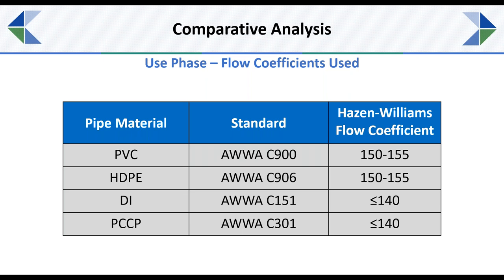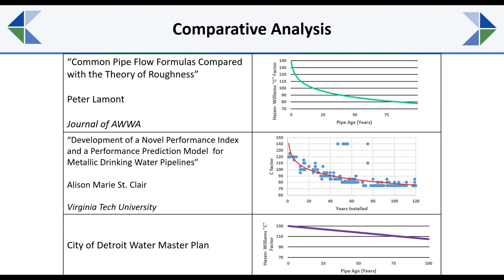Your mortar lined or concrete lined products, such as ductile iron or PCCP, have a slightly lower one, and that value actually is affected by the age of the product. And I'll actually show you where we kind of determined that. We looked at different reports that were out there, and those reports consistently showed that mortar lined materials do have a decreasing flow factor over time. So it was difficult to determine what the average or best value to use was. We tried to use something that was more favorable to those mortar lined or concrete lined materials.